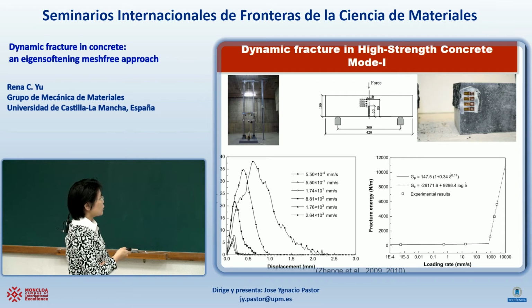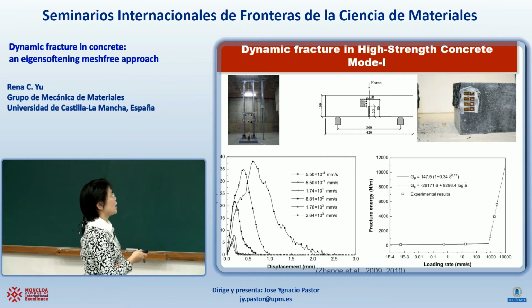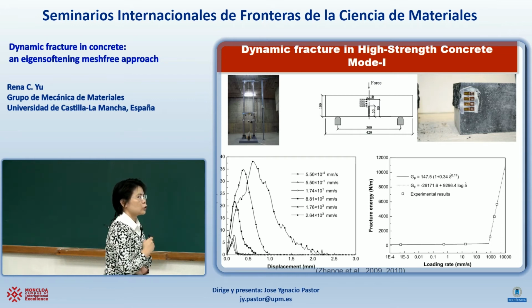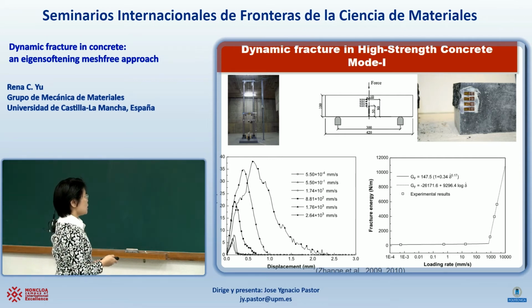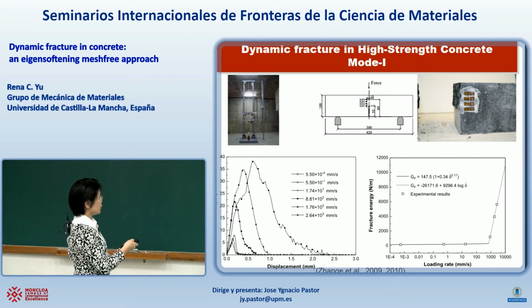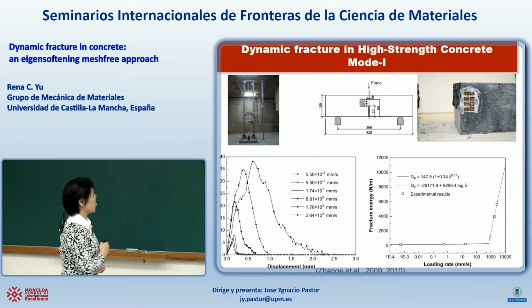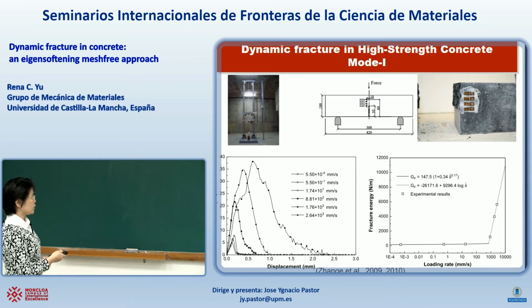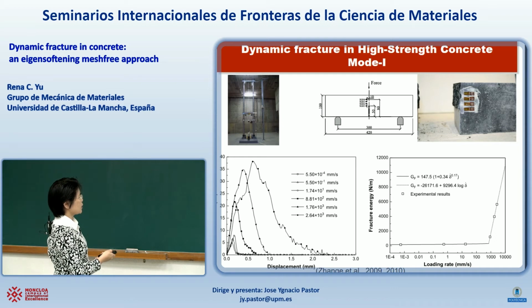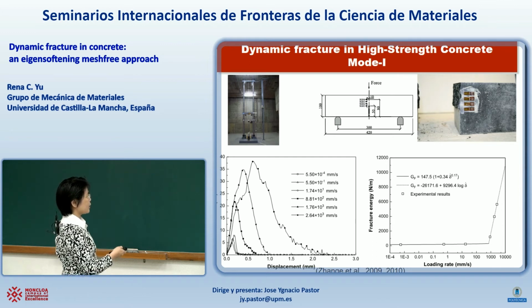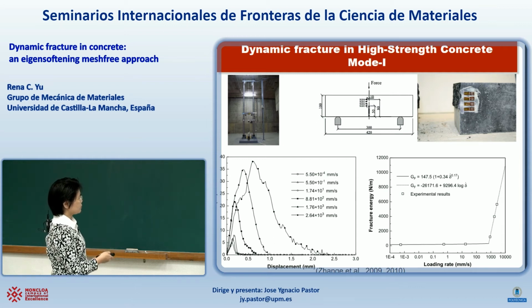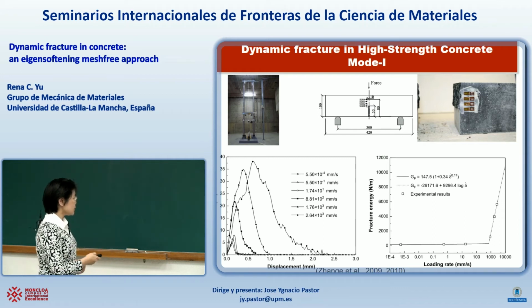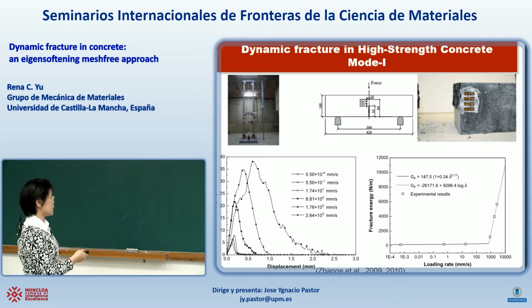And parallel to the center section, there were 4 strain gauges glued there to measure the strain history. Additionally measured at these 2 supports is the reaction load. What I show here is the loading line displacement, which is around here, and this is the reaction load that is measured from the 2 supports. What we see here is that these were actually the first 3 curves for the loading velocity. That is 10 to the minus 4, 10 to the minus 1, and this is like 17. These were carried out with a hydraulic machine, while these 3 were carried out by the drop weight test machine. What we see here is that the reaction load increased significantly in the dynamic case.